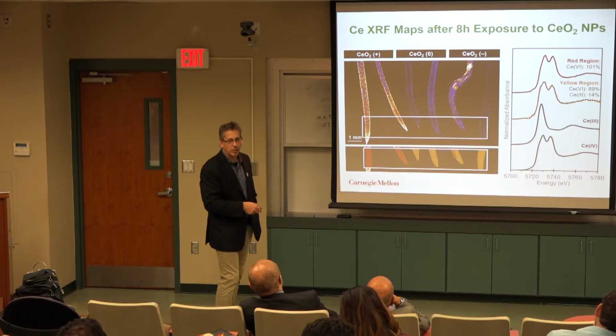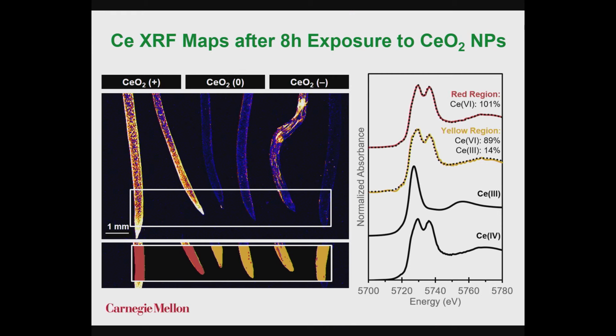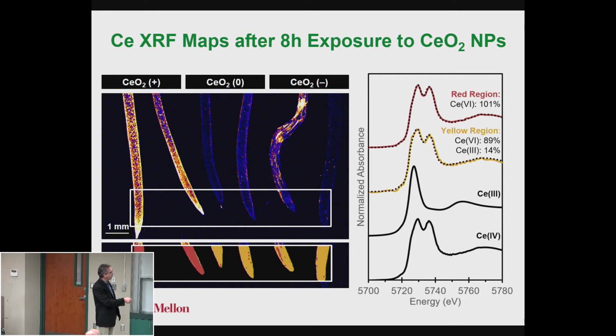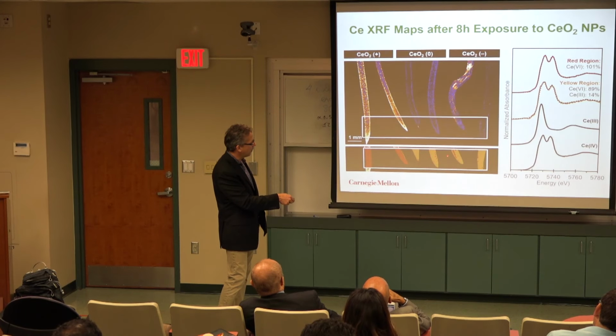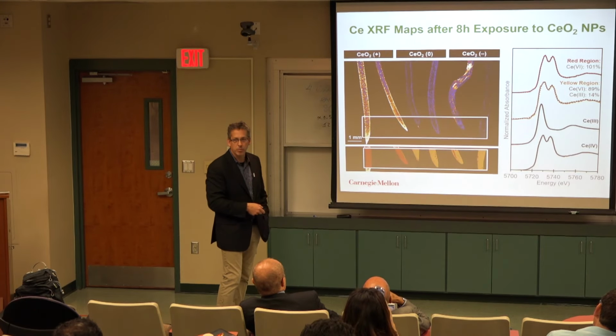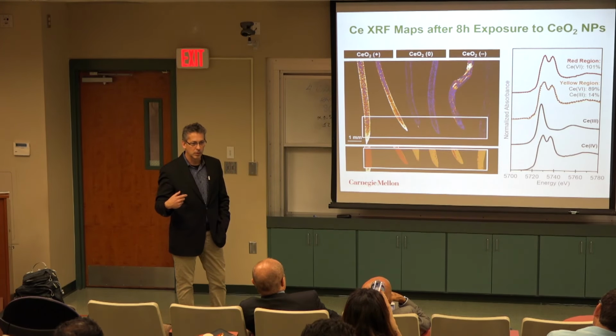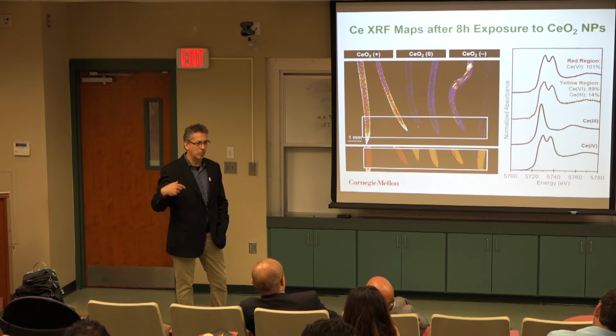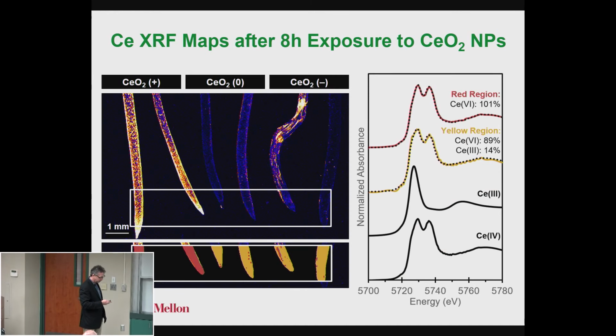It's almost all cerium-4. It's almost all those nanoparticles we put in because there's so much, it's all we can see. But for the ones that have a lot less cerium in the root tips, some of that cerium, not all, but some of it has been converted to cerium-3. It's been reduced. Now, we don't know yet if that's free cerium-3 or cerium-3 associated with the particles. We believe it's dissolved and free cerium-3. Okay, so that's kind of interesting.